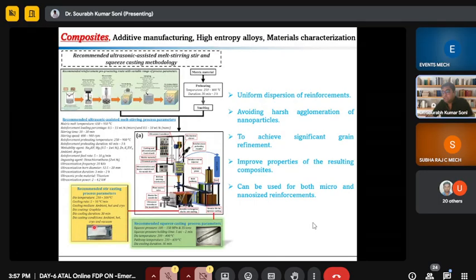This is the stir casting sample, and this is the squeeze casting sample. From this setup, we can achieve uniform dispersion of reinforcement. We will avoid the harsh agglomeration of nanoparticles, specifically nanoparticles, I am saying that. And we can achieve significant grain refinement and improved properties of the resulting composites, and it can be used for both micro and nano size reinforcement.